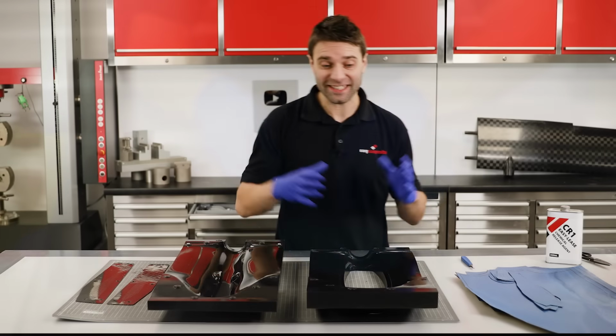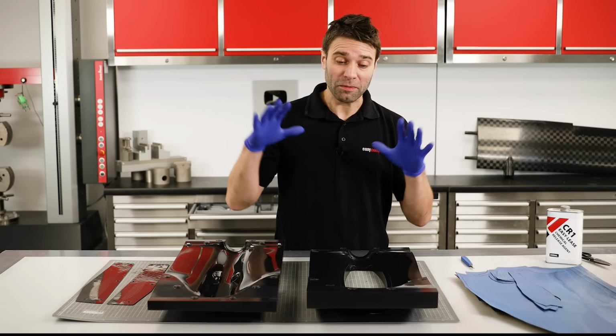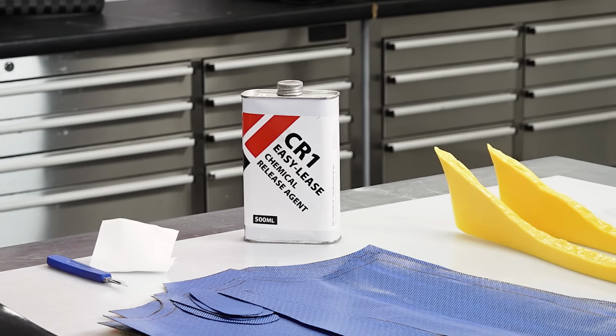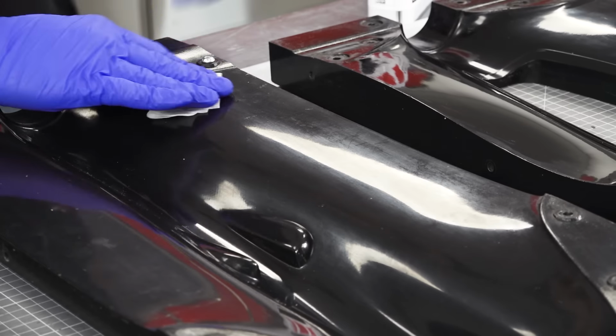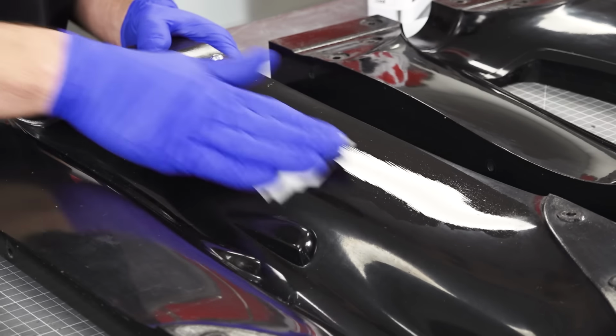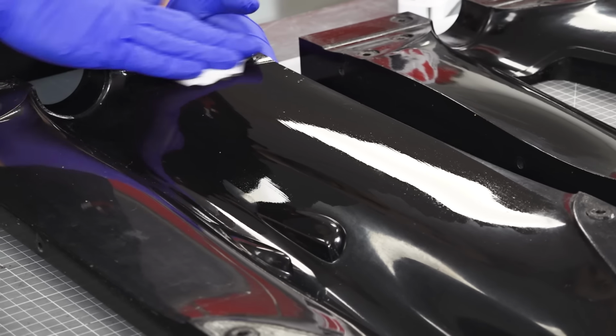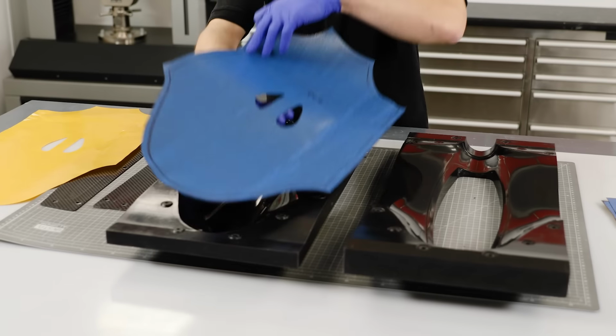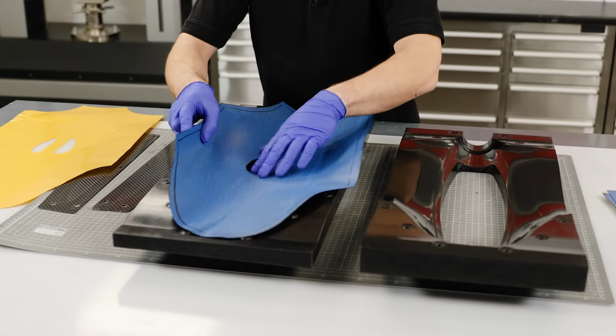So that's everything set ready to get started into the layup. Before I do though, I'm just going to give these a quick top up with release agent. A coat of Easy-Lease CR1 is applied to all of the mould faces with a lint-free wipe, allowed to cure, and then the prepreg is laminated down.